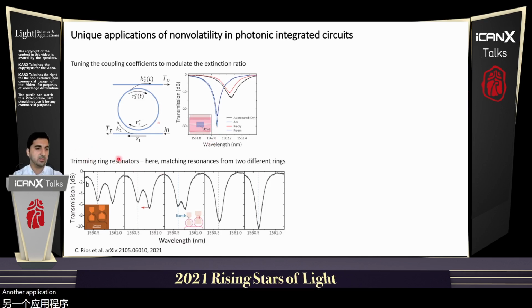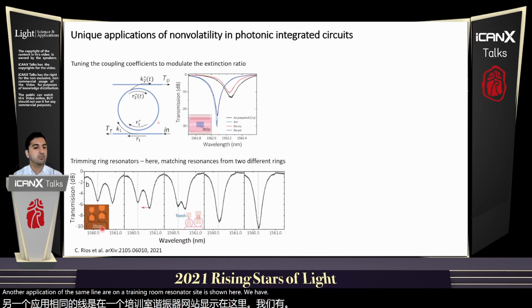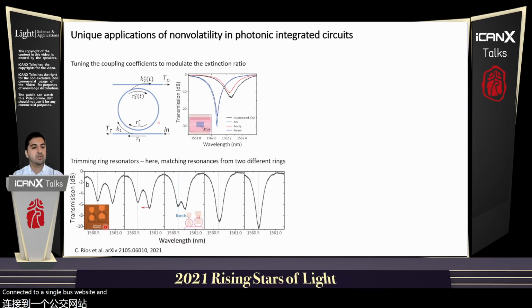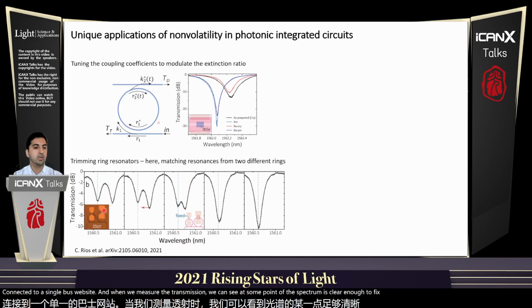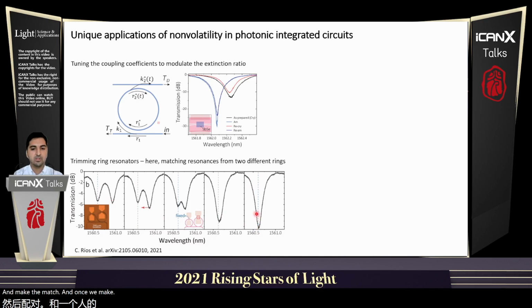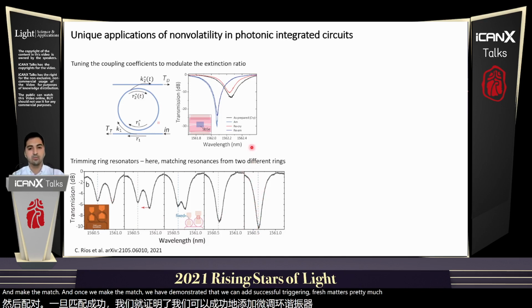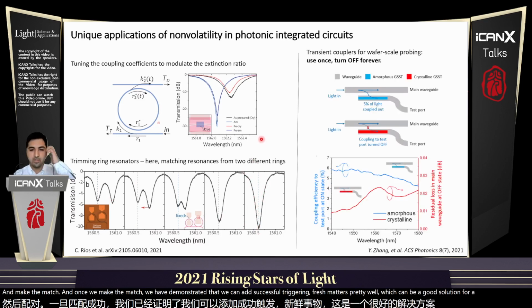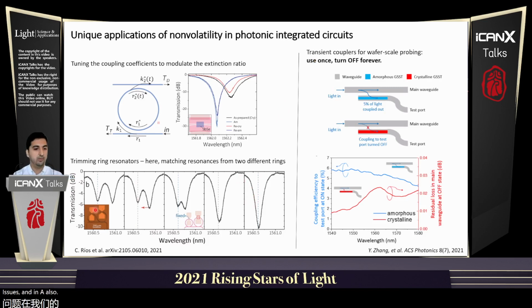Another application along the same line, on trimming ring resonators, is shown here. We have 2 different ring resonators, the image is here, connected to a single bus waveguide. When we measure the transmission, we can see at some points of the spectrum a splitting of 2 peaks. What we can do is move one of those and make them match. Once we make them match, we are demonstrating that we can successfully trim ring resonators pretty well, which can be a good solution for fabrication issues, and also for engineering the dispersion within these ring resonators.